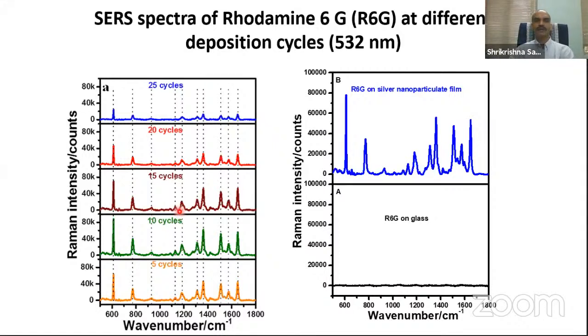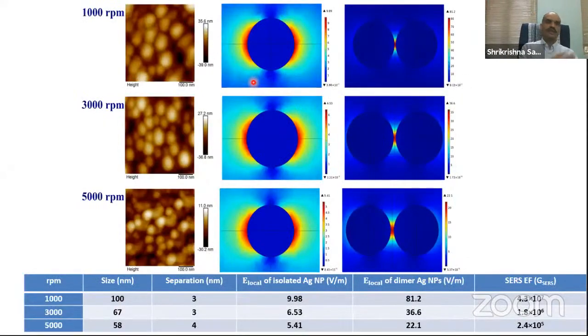This is 80K for this R6G. That's first. So from nothing to everything you can get. You see that when I put this rhodamine 6G, a probe molecule, on glass, I get 0 intensity. But if I put it on the silver nanoparticles, you get very high intensity. Similarly, you can do the simulation, and from this simulation you can see how much the electric field is increased.